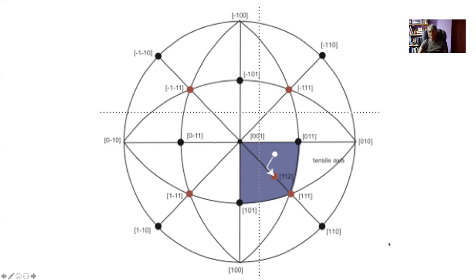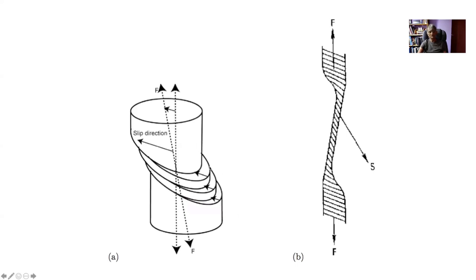When the tensile axis hits a corner, many slip systems become equally stressed, but in practice work hardening and interference between slip systems means they rarely operate equally. In summary, slip either moves the force axis to a new orientation or, if the force axis is kept fixed, the crystal itself rotates relative to the force axis.